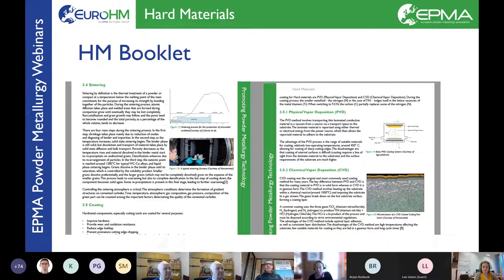As Luis mentioned, it's very important from the application point of view to have the right dimensions of your cemented carbide part. And the most important step in controlling the dimensions is the pressing in combination with the sintering. During the sintering step, we have a debinding process during the sintering cycle. And then after the debinding, you reduce the tungsten oxides and the cobalt starts spreading across the tungsten carbide surfaces.